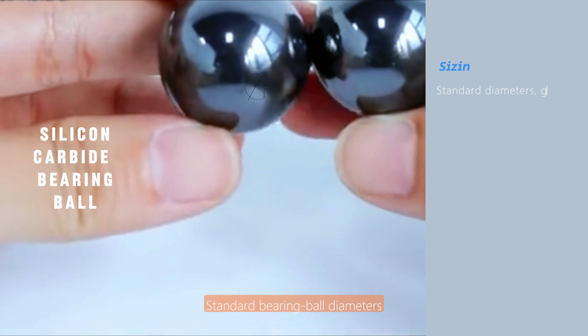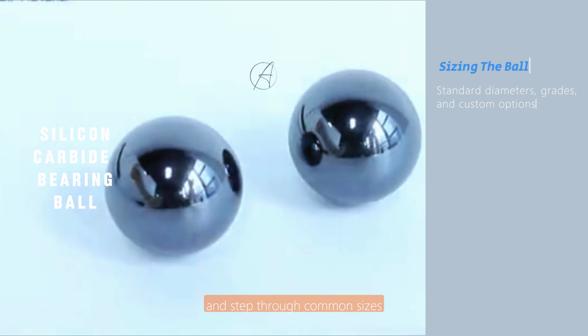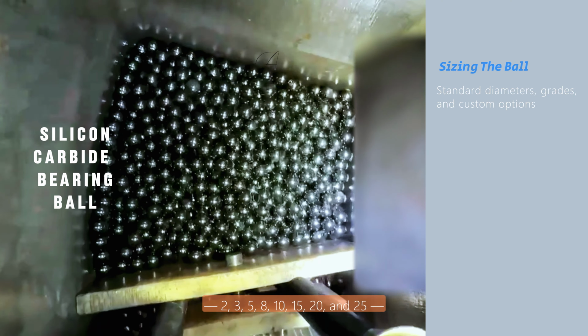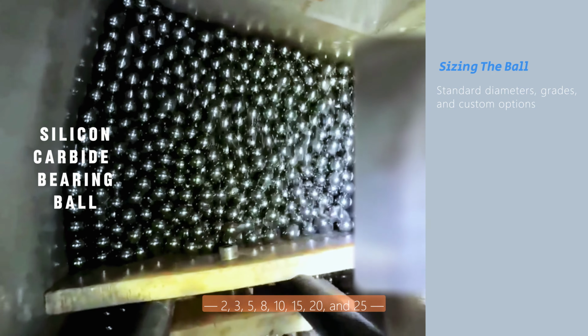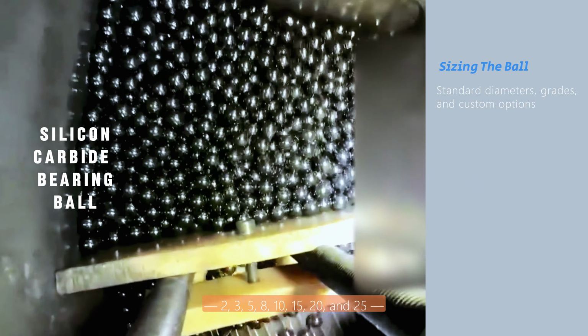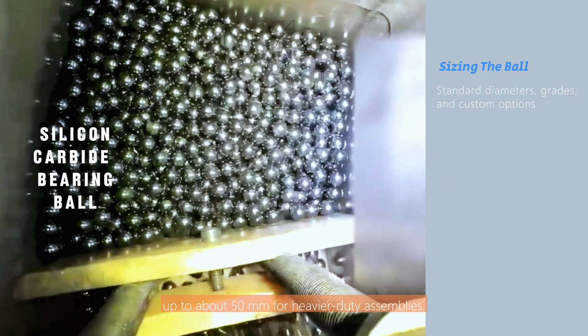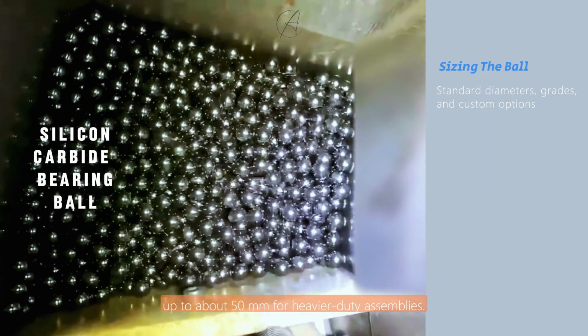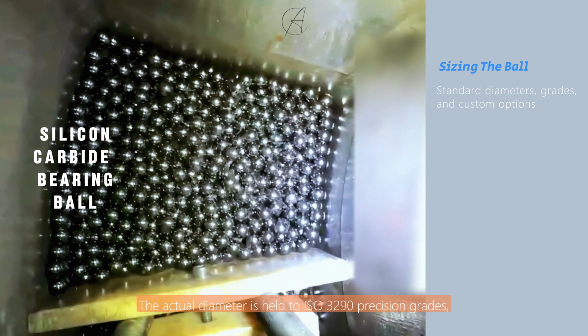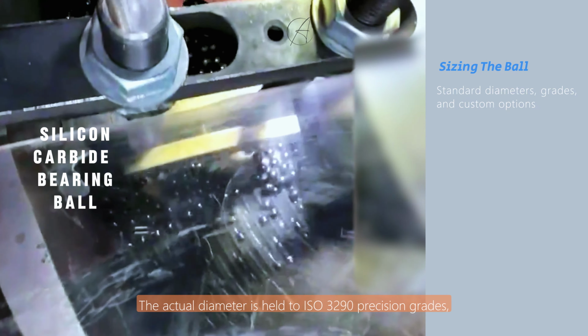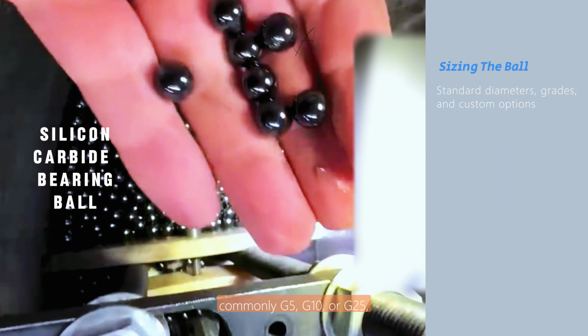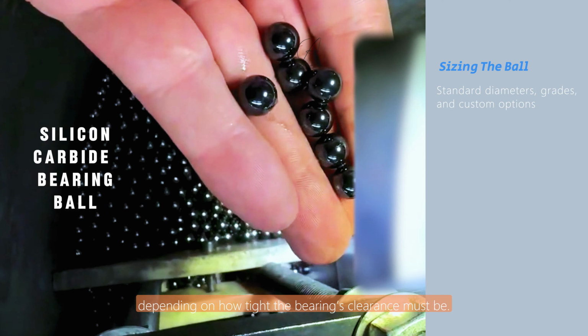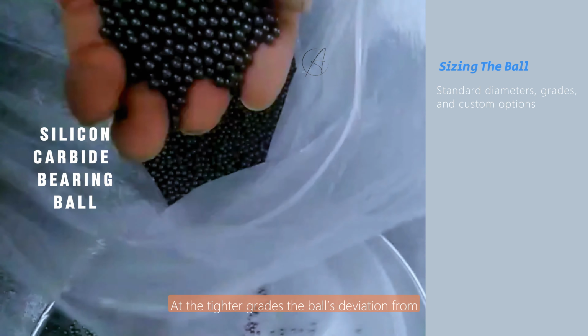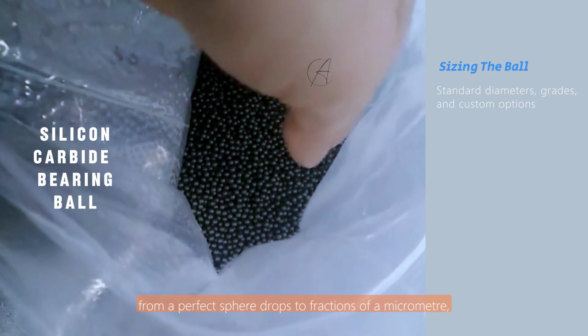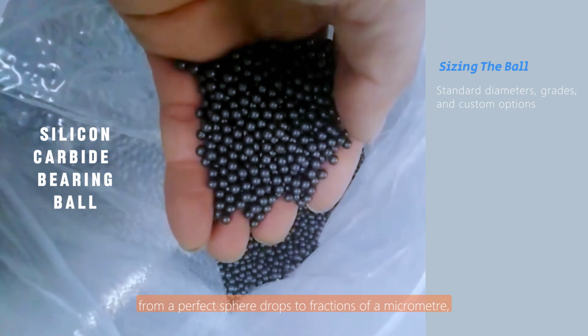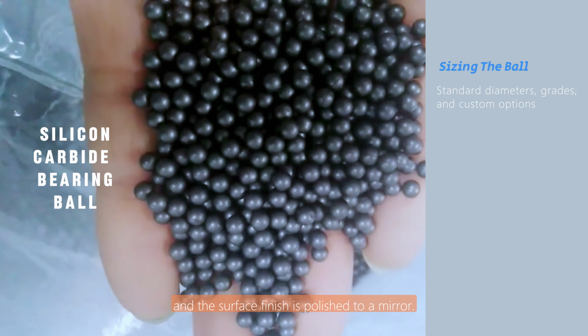Standard bearing ball diameters typically start near 1 mm and step through common sizes 2, 3, 5, 8, 10, 15, 20, and 25, up to about 50 mm for heavier duty assemblies. The actual diameter is held to ISO 3290 precision grades, commonly G5, G10, or G25, depending on how tight the bearing's clearance must be. At the tighter grades, the ball's deviation from a perfect sphere drops to fractions of a micrometer, and the surface finish is polished to a mirror.